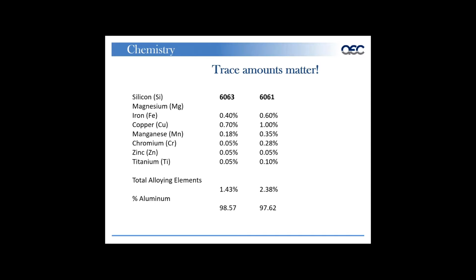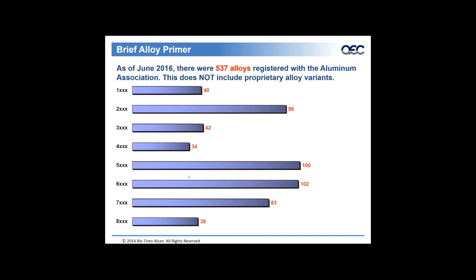Trace amounts matter in regards to chemistry. So here's an example of a 6063 alloy and a 6061 alloy. We can see the total alloying elements are represented by less than 3% relative to percent aluminum. As we saw in the prior slide, there is a difference in mechanical properties between a 6063 and a 6061. But this represents what minimal difference there may be in a specific alloy, for example your iron, copper, manganese, magnesium, zinc, titanium. So trace amounts matter.